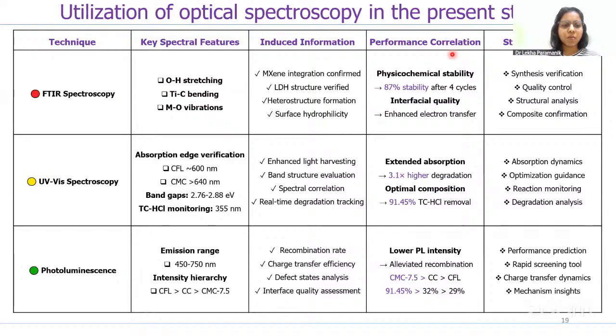This is a complete comparative tabulated summary of my results. From FTIR spectroscopy, I was able to determine the structural integrity was confirmed, and from the UV visible spectroscopy, I concluded that with the modification, the absorbance has increased, and as a result, the activity rate has been highly improved. The photoluminescence spectroscopy produced emission peaks across the range 450 to 750, and with the intensity comparison, I found that my CMC 7.5 has a very high charge transfer efficiency.